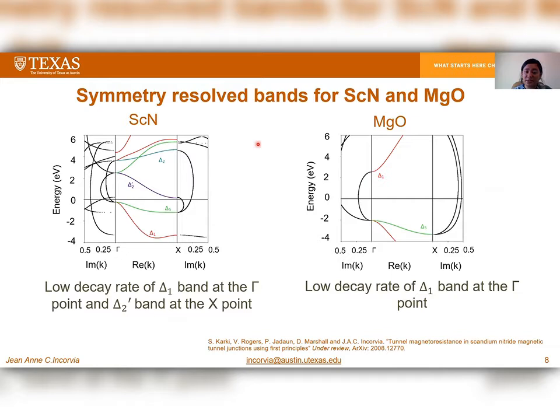Further on, we looked at the symmetry resolved bands for ScN and MgO. On the left is ScN, where we can see that the real k-space is sandwiched between the two imaginary k-space, and we find delta 1 bands and delta 2 prime bands with very low decay rates, the delta 1 band being at the gamma point and the delta 2 prime band being at the X point.